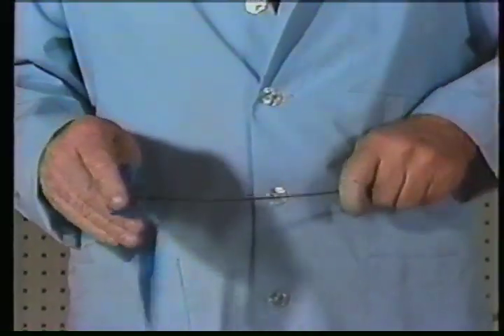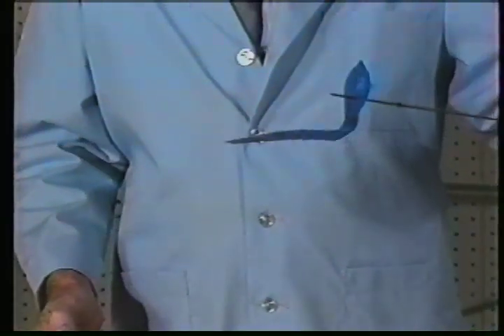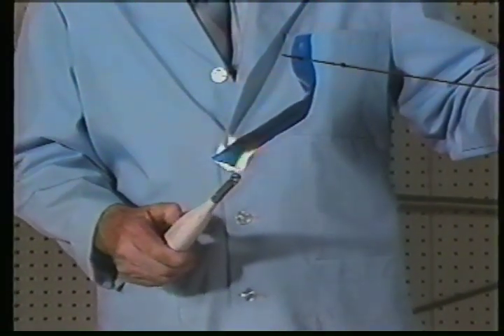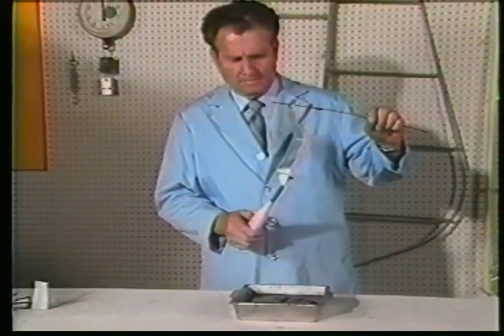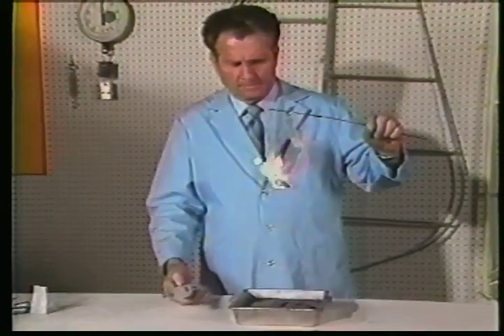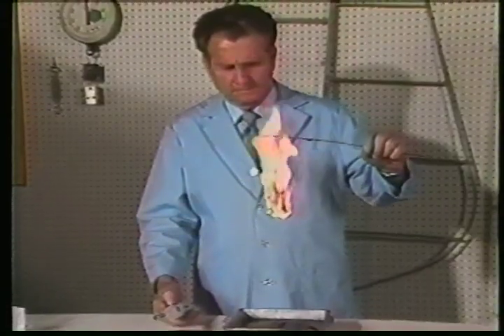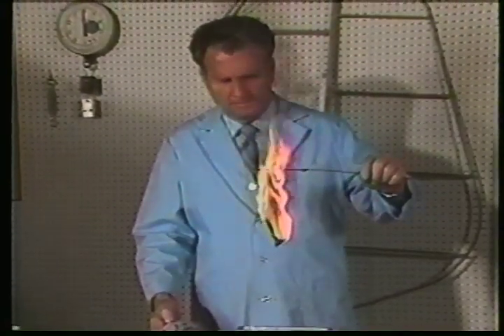Next is a sample of blue-tinted nitrate dope called DAC-proofer, claimed by the manufacturer to give a complete fire-retardant system with 2 coats on polyester fabric. Don't bet your life on it. This sample burns just as fast and hot as untinted nitrate dope. Next is aluminum pigmented nitrate dope on polyester, which burns with a noticeable sparkle due to the aluminum pigments.